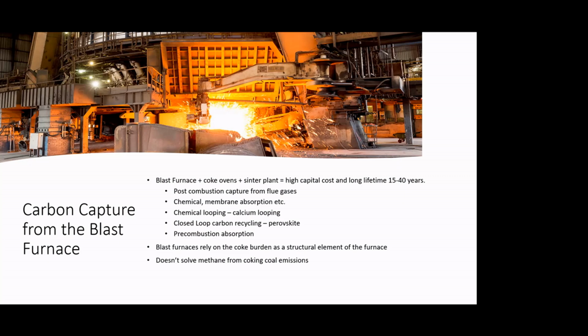But one of the problems with blast furnaces and with replacing the fuel is that the coke is actually a structural element, and the structure of the coke burden is a really important part of iron making. You cannot do without that in a blast furnace. It also doesn't solve the problems to do with mining coking coal.